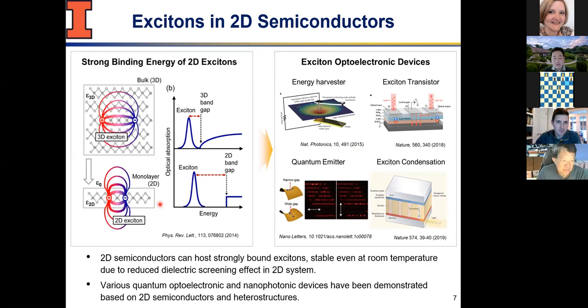And what that means from this electron hole pair point of view is their binding energy. So in a typical semiconductor, we barely explain electron as electron hole pair, although we know when you shine light, electron will get to excited state and you have a hole at the valence band, you have electron hole pair, but we don't think of it that way because they are heavily screened, so we can think of electrons or holes. Here, the screening is so little, now you have to treat them together. So there's extra energy you need to consider, or you have to treat an excited electron as electron hole pair in the 2D semiconductor, which we call excitons. That's nothing but electron hole pair with a good binding against the thermal fluctuation.